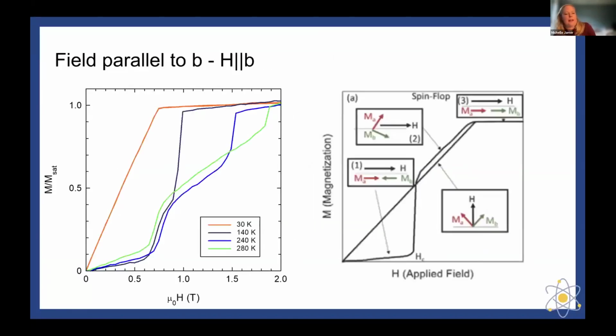So if we were to look at the field parallel to the B axis, what we'll see is that at different temperatures, it behaves differently. What we see is at 30 Kelvin, even along the B axis, it starts to look like that linear magnetization up into this inflection point, and then it saturates. And as we increase the temperature, we see the changes of the inflection points through the helical spin spiral state. So if you remember, whenever you're below about 68 Kelvin, you're in that first ferromagnetic state. Whenever you're above that 68 Kelvin, that's when you're starting to get the antiferromagnetic ordering. So we can kind of compare this to a spin flop based on how the magnetization looks.